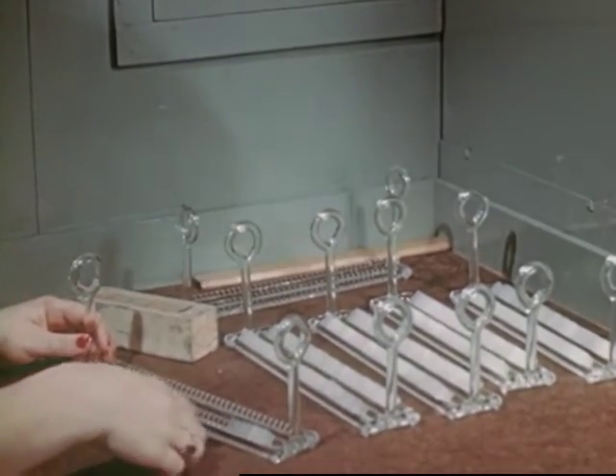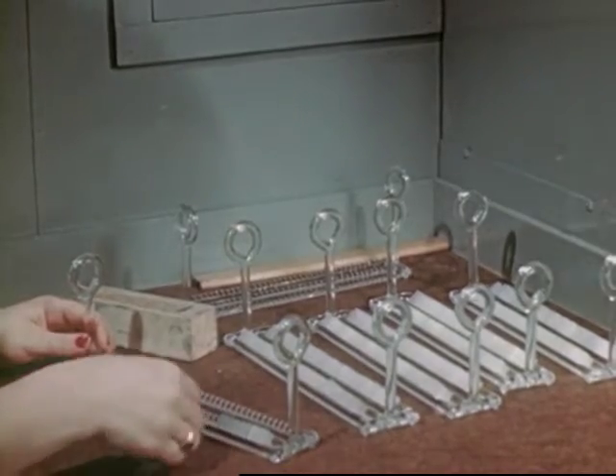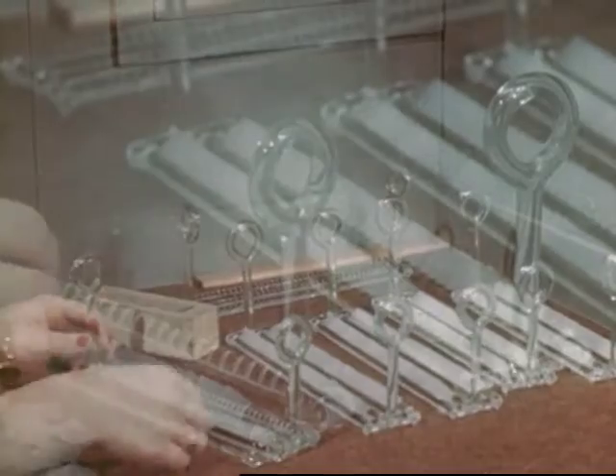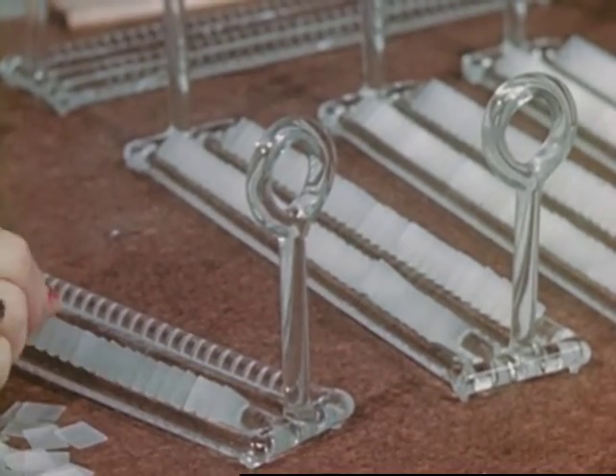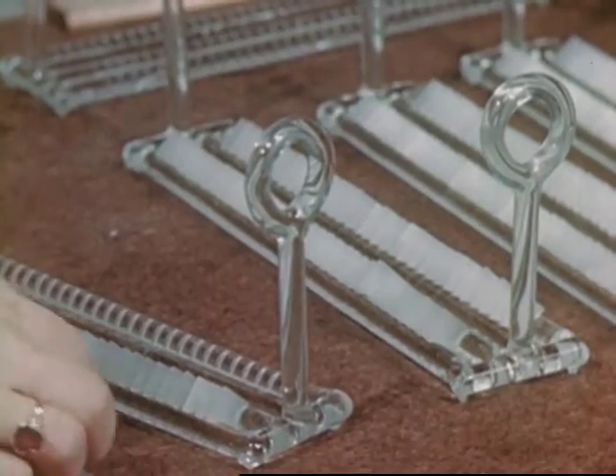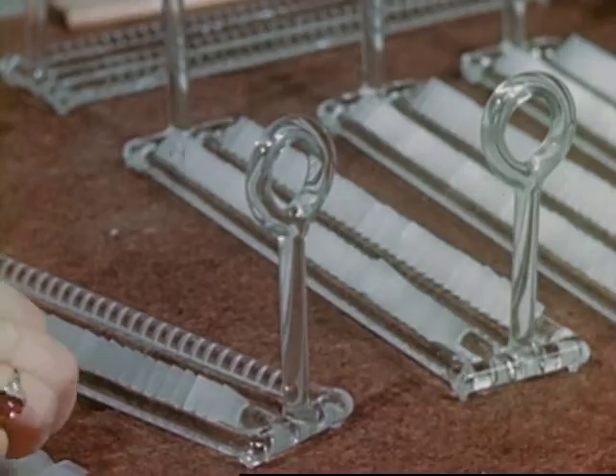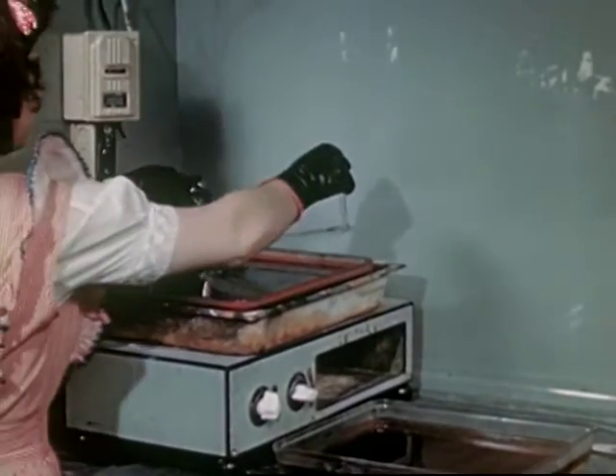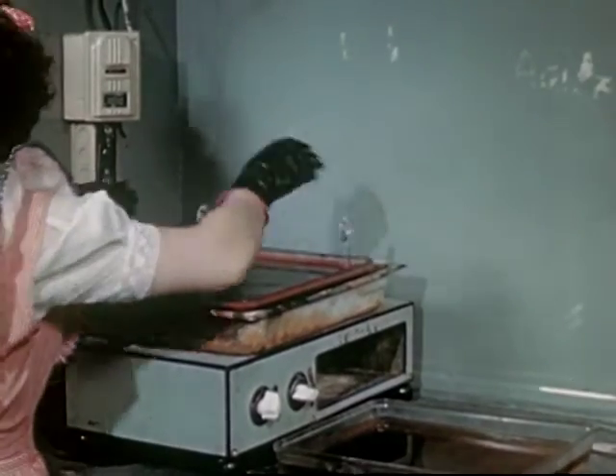In the final finishing department, the crystals are etched, first in mass and then individually by hand, to bring them up to the various specified frequencies. Preparatory to the mass etching operation, the crystals are stacked in notched Pyrex glass racks and are given a final cleansing in a concentrated chromic acid solution. The crystals are first thoroughly cleaned to remove abrasive and oil left by the machine lapping process.